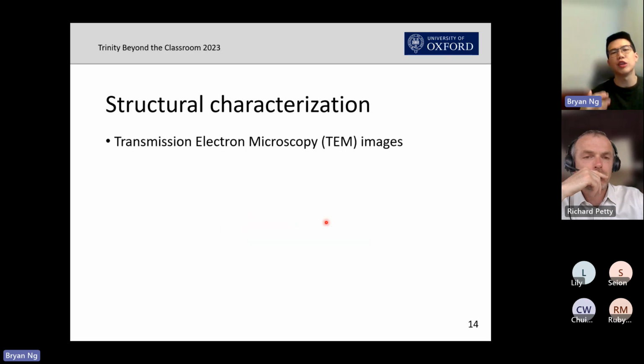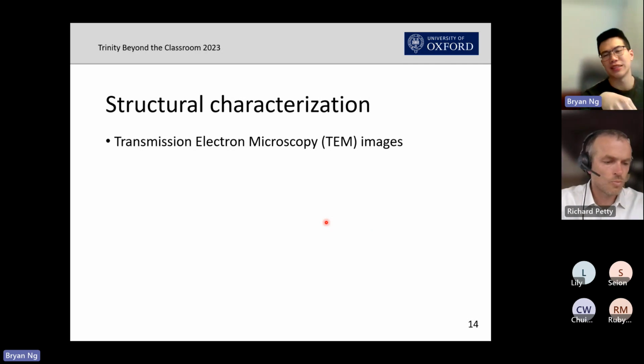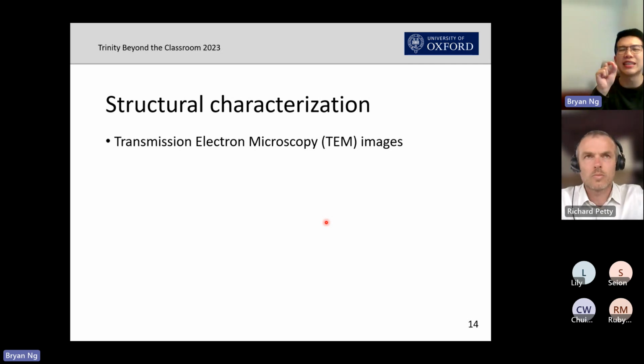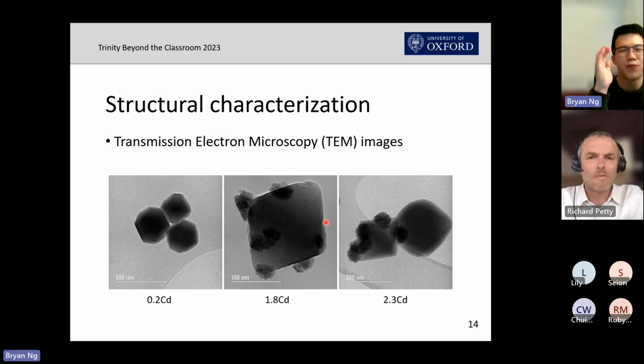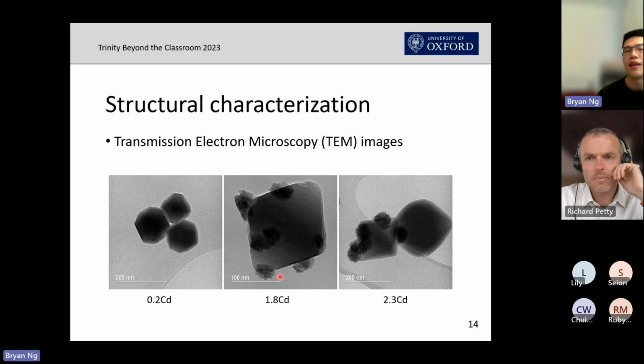And then the other structural characterization, I picked this one because it's kind of the most obvious in one sense. You are zooming in very, very close to see exactly what it looks like, taking a very tiny photograph of what your samples look like. So these quite look like octahedra. These are my MOF materials, the metal organic frameworks themselves. And then there is some cadmium sulfide. I think these are the cadmium sulfide that are deposited on the MOFs. For these two samples, they both consist of these darker spots.